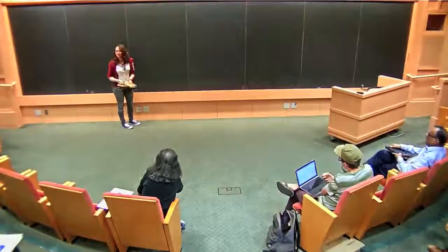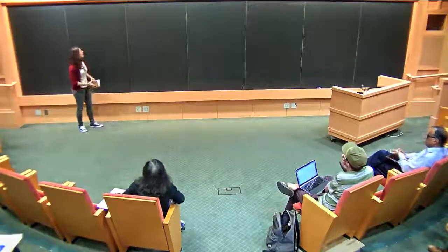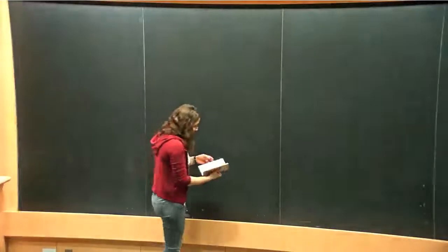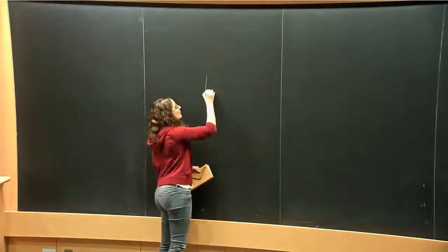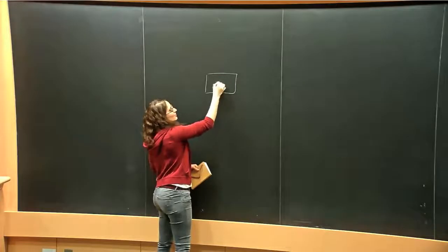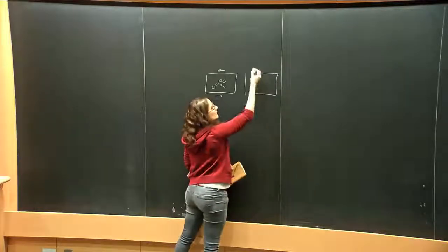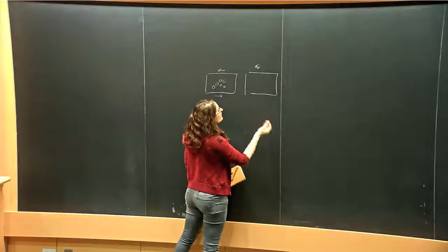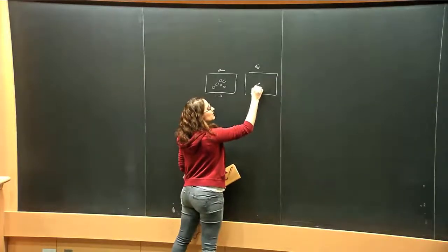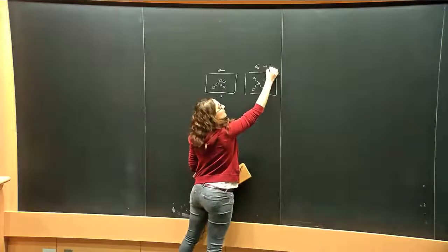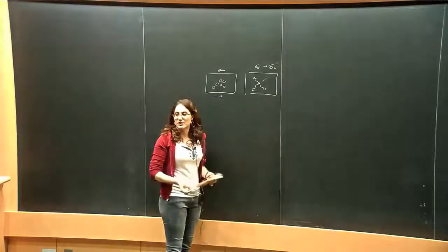So actually, I've been working on mesoscopic elastoplastic models, and I think many of the ingredients that you put in those models can be discussed here, given all the talks we had today and during the week. I just want to sketch briefly the main ingredients, and then we can talk about it. The elastoplastic scenario is the one that you all know: when you deform some amorphous material, at first you have an elastic deformation, and when a given threshold is reached, typically a local yield stress sigma c, you will locally have a plastic rearrangement that will propagate the stress to the rest of the system, and locally you will pick up a new value of local yield stress because of the local rearrangement.